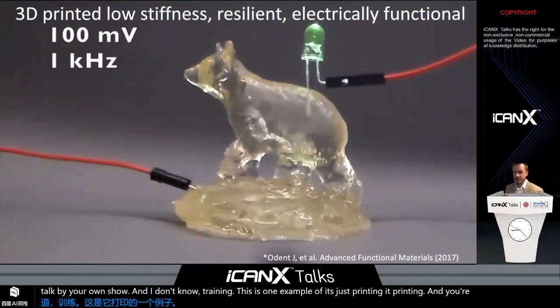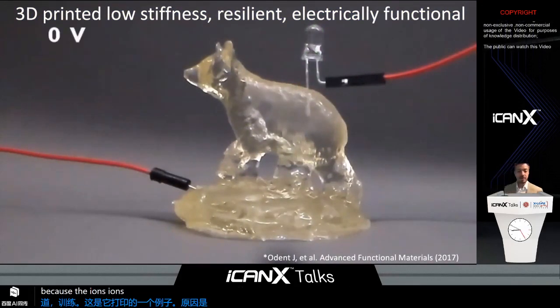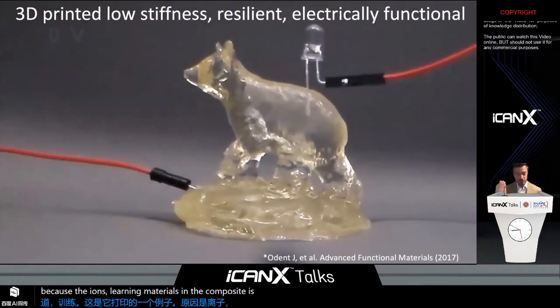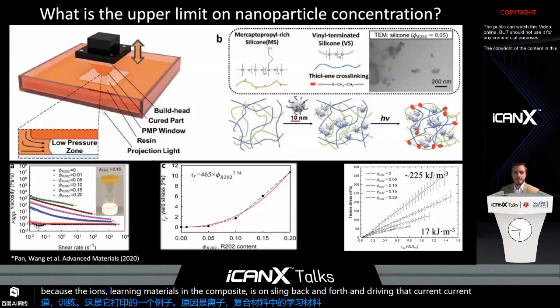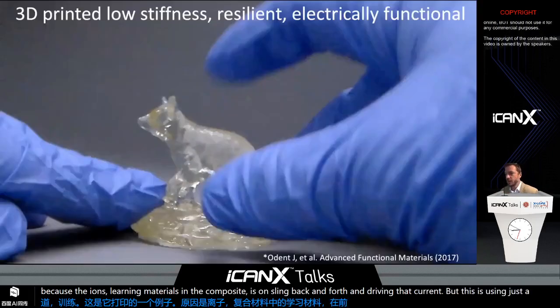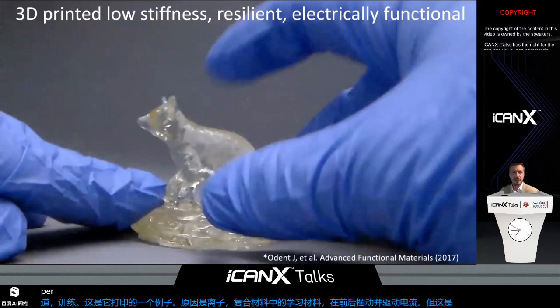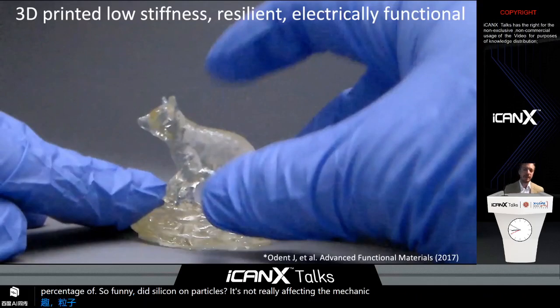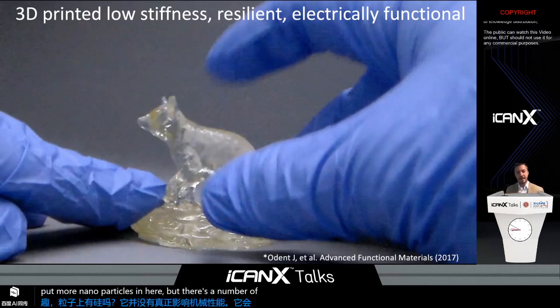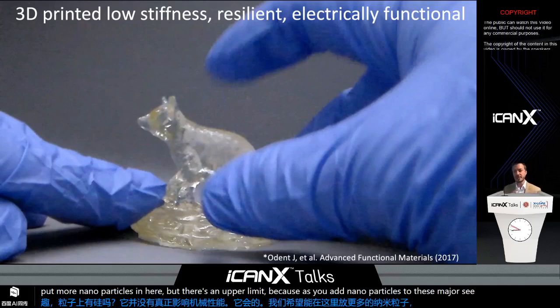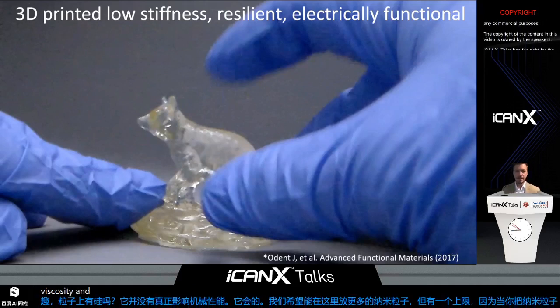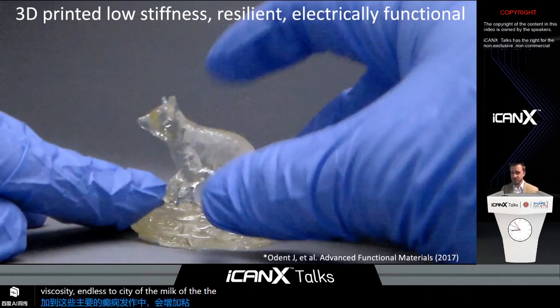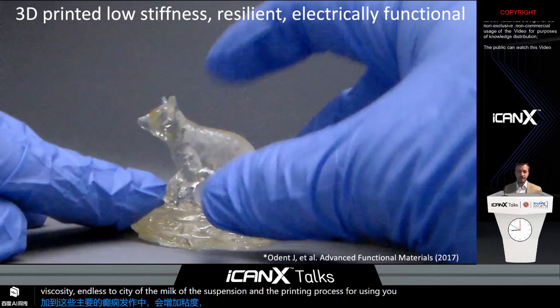And the reason this is working is because the ionic material in the composite is oscillating back and forth and driving that current. But this is using just a few percent of sulfonated silica nanoparticles. It's not really affecting the mechanical properties. We would love to be able to put more nanoparticles in here, but there's an upper limit, because as you add nanoparticles to these matrices, you're increasing the viscosity and elasticity of the suspension. And the printing process we're using doesn't like that.